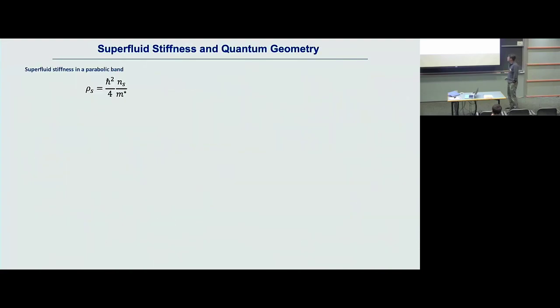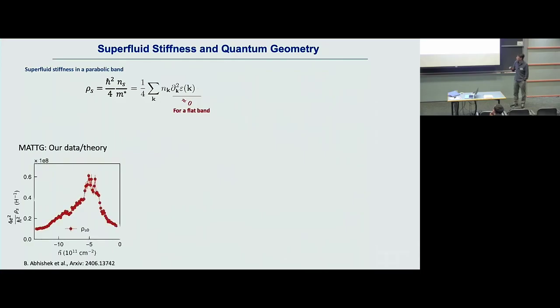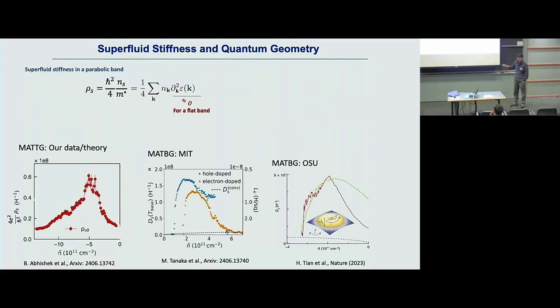Okay, as a summary, before closing down, one open question I want to ask is about the absolute magnitude of this measurement. I mentioned that we have the superfluid stiffness, and now I convert it in terms of Henry. In fact, that is comparable to the ranges of all other measurements, including the MIT measurement I mentioned. It's about the same order. Now this magnitude is much larger than what is expected from just putting in the effective heavy mass computed. It's about an order of magnitude larger.